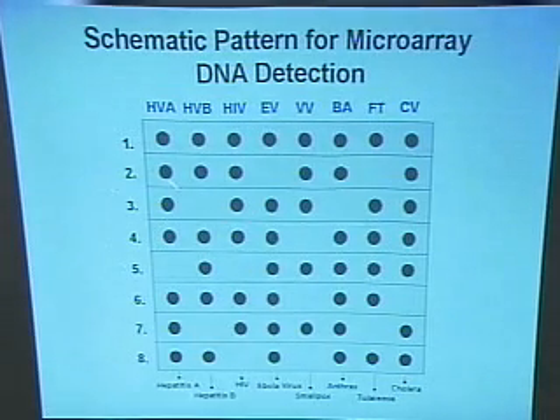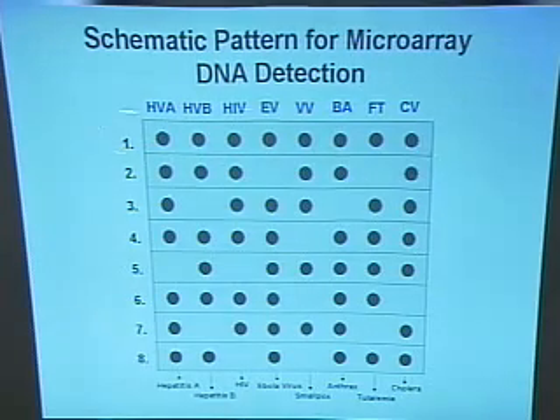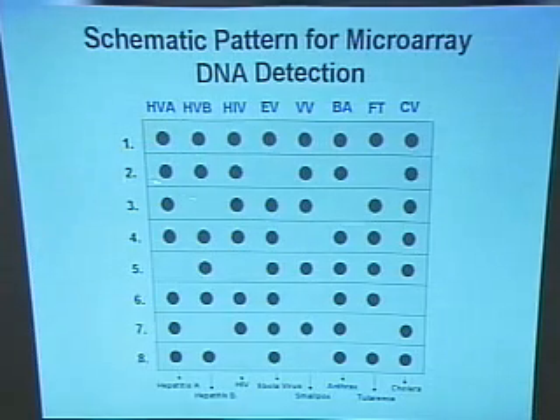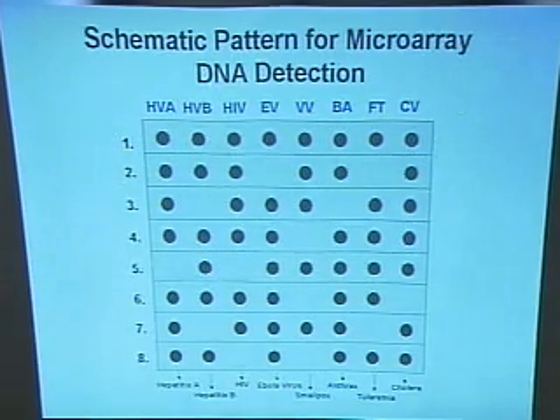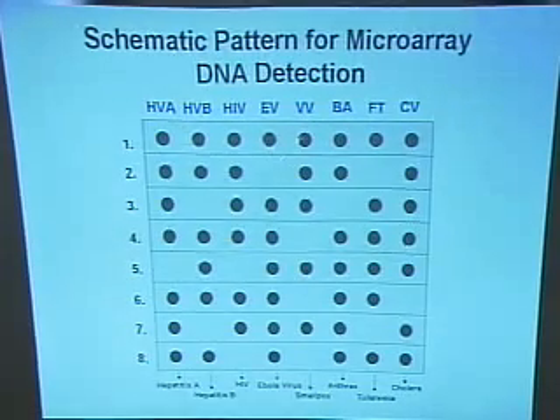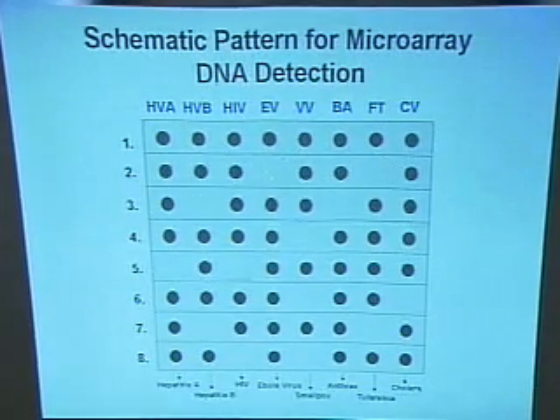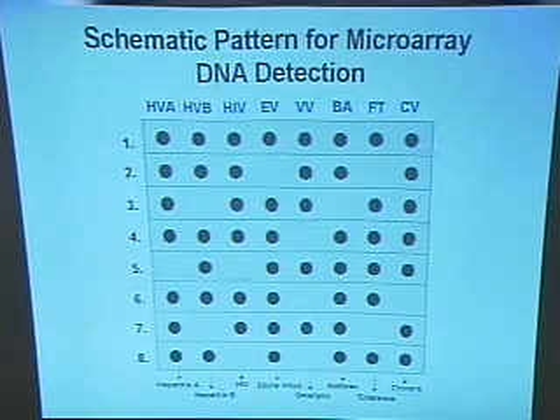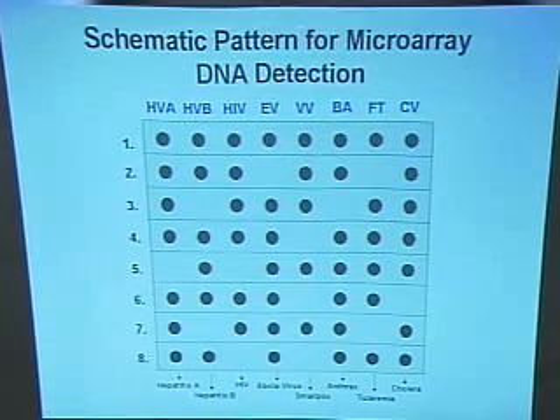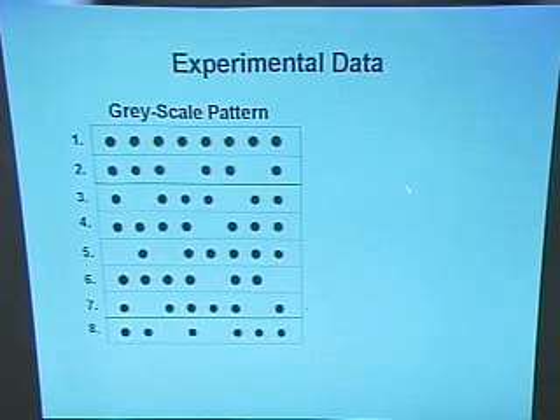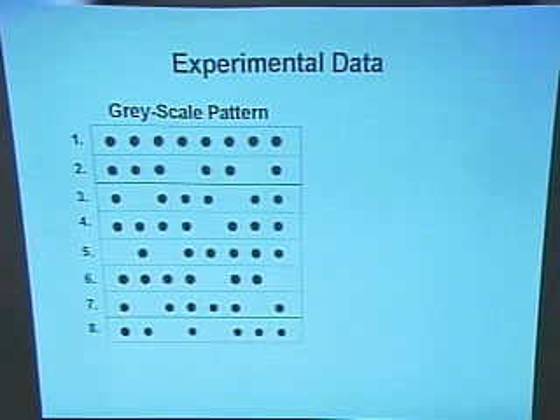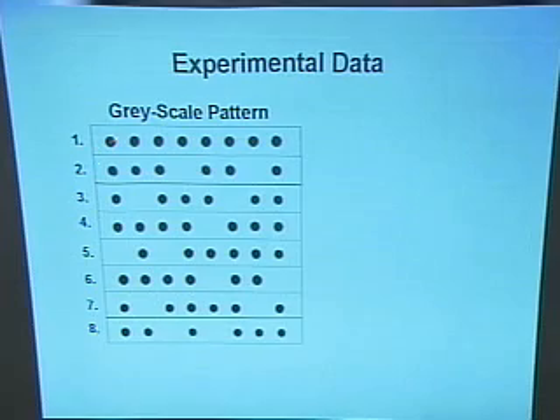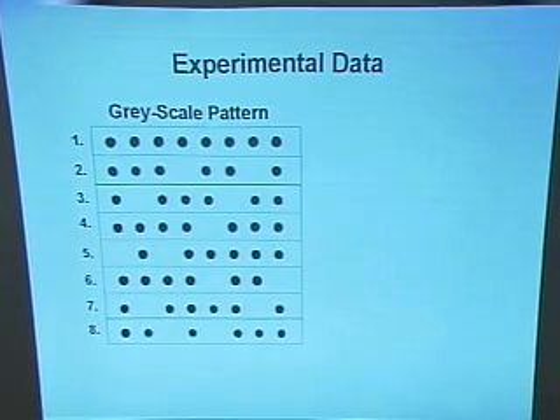For the first test, all the targets are present, so we should get 8 spots. In the second one, we take off this target, and in the third, we take off this one. Now, how about our experimental result? We found it follows exactly this cartoon. However, if you look at the black spots, you couldn't tell which target is which.